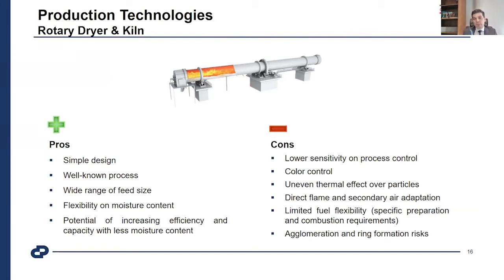It has a little lower sensitivity on process control because you cannot check inside the kiln meter by meter, and you cannot control it. You just get the output material, especially if the feed material is not homogeneous in both moisture and mineralogical composition. It causes deviations in the final product.